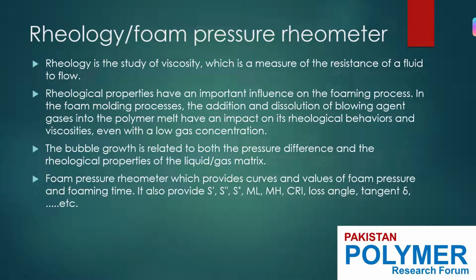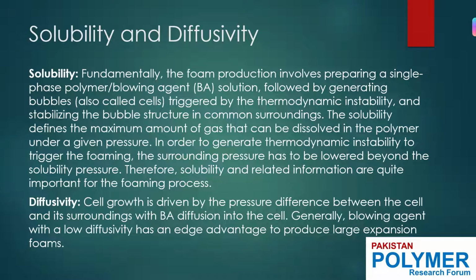In polymer forming, the melt flow properties are also influenced by the blowing agent because the blowing agent can increase the polymer free volume and chain mobility. That's why customized rheometers can also be used to measure the rheological properties of the processes. And I'll be talking about the foam pressure rheometer in my work to measure the rheological properties of the polyolefin foam process. After rheology, I'll be talking now about solubility and diffusivity measurements.